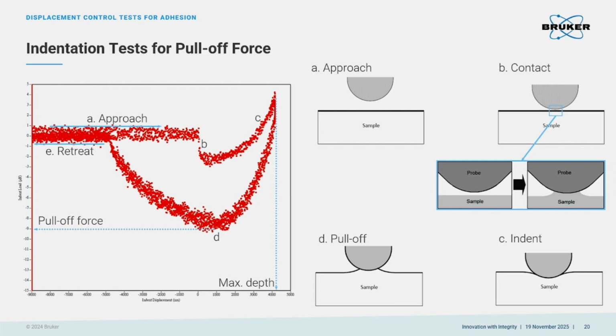to speed or to rate. So the first viewpoint I would like to share with you is the pull-off force test. So the idea is, we get the probe far away from the sample at the beginning, and then approach the sample, get the probe down to approach the sample. Then we will have a so-called jump into contact point like this if the sample surface is viscoelastic. These things typically happen very suddenly. So we have this B point we typically call the jump into contact point. And then the probe starts to make contact with the sample surface.